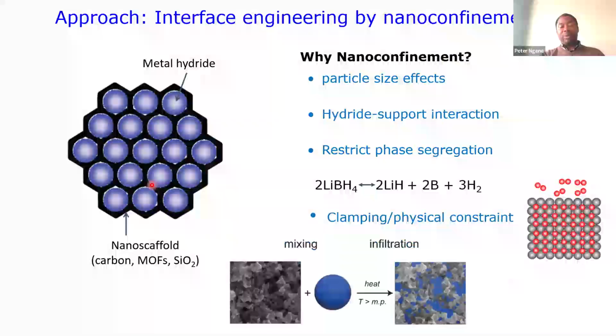So why do we want to do this? There are so many benefits of doing this. The idea is that when we do that, you can actually reduce the particle size. We do know that when the particle size is small, you can enhance mass transport, and the kinetics will be highly enhanced. Another thing is that there could be hydride-support interaction. There could be some kind of interaction that could be beneficial towards changing, destabilizing or stabilizing this hydride because of this interaction. And then you can also restrict phase segregation. Why do I talk about phase segregation?